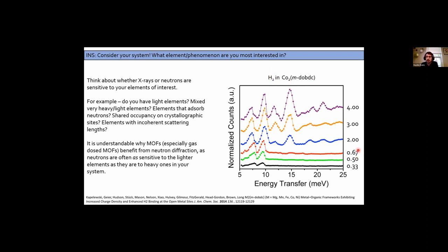Depending on the levels that you dose the hydrogen in, so these are mole equivalents to the cobalt here, you can see that you get these low energy transfers start to grow in. And then once you start to add more than one mole equivalent, you start to access these other sites. But those sites then start to be impacted because they're having some sort of interaction with the hydrogens that have been absorbed. This peak starts to shift to the higher energies and this peak starts to shift to the lower energies, and this gets more and more exaggerated as you get more and more dosing in.